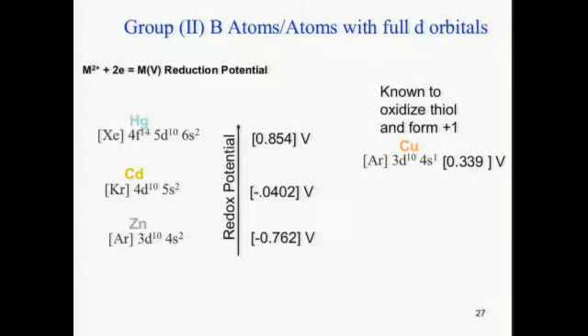Beyond that, I thought not only can I look at different molecules, but how about looking at different atoms as connectors? I was interested in transition metal atoms that like the +2 oxidation state. I also thought about the periodic trend and looking at their redox potentials. I thought it would be nice to show that fundamentally, if you just look at the periodic table, you would not expect these to make a multilayer, because the redox potential does not lend itself to oxidizing the sulfur to either a disulfide or just as a catalyst or a connector between the 2 sulfurs. But you might get somewhere with mercury, and we already knew we could get there with copper.